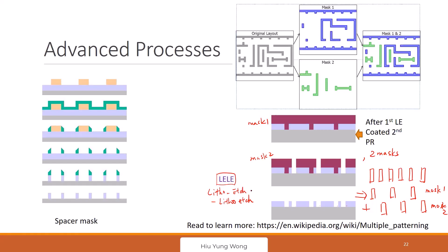Now, another thing is that we don't use the mask. We use so-called spacer. I can pattern this. This is wide, easy to pattern. But you know, this is not what I want. After this, they deposit spacer. It's just a conformal layer. And then we etch it. When you etch spacer, because this is thicker, so they left over. And then I remove the mask. This becomes my mask. And then I etch them. Then I am able to get this small pattern.